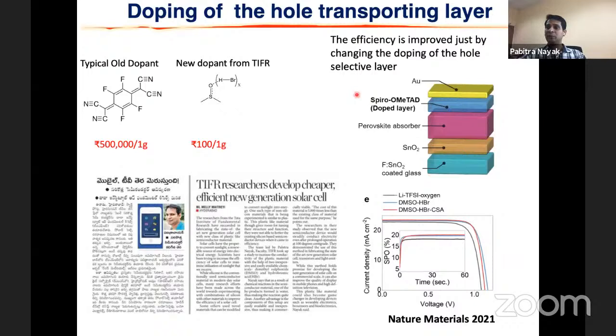I only talked about how to generate the charges and give them directionality. But if there are too many, you need to take them out nicely, right? If you can't take them out, then the efficiency will be less. So people generally use a very expensive material to do that. It's like 5 lakh rupees for 1 gram. From TIFR, we came up with a very cheap alternative to that, and it even works better than this material.